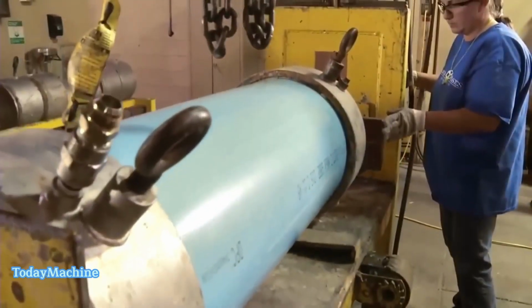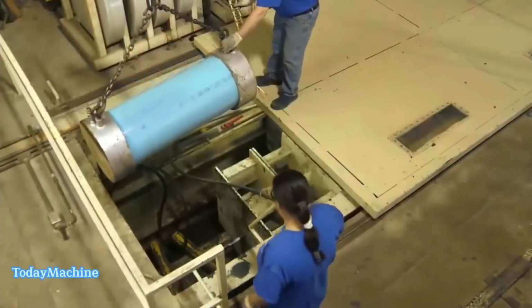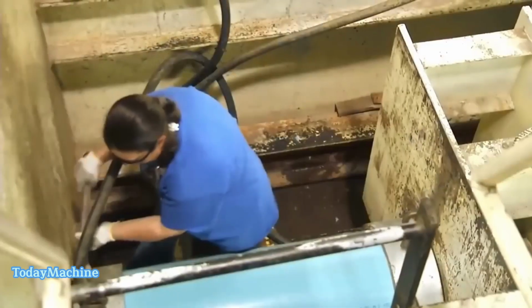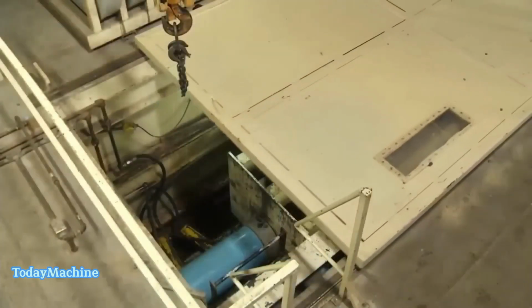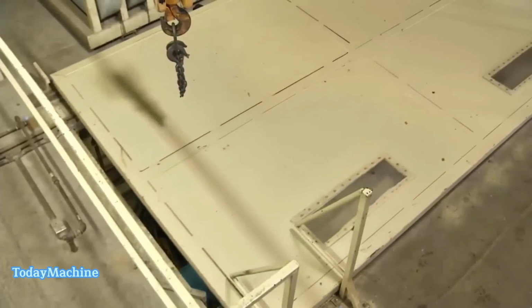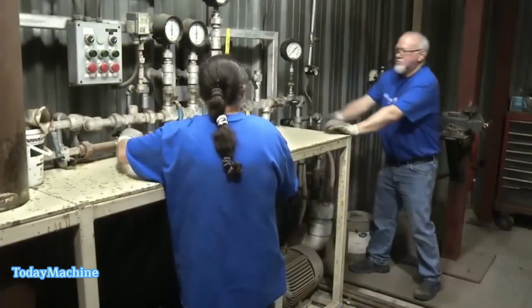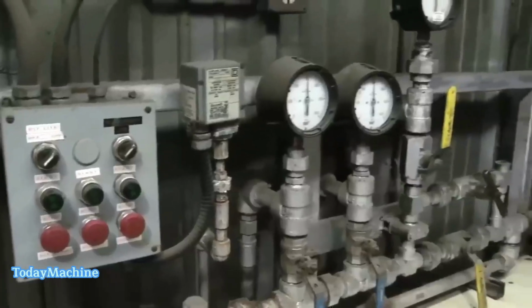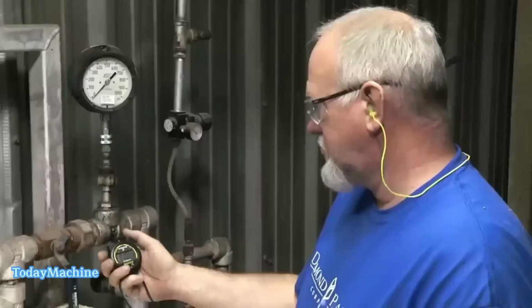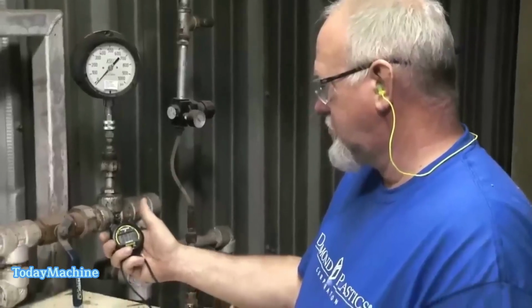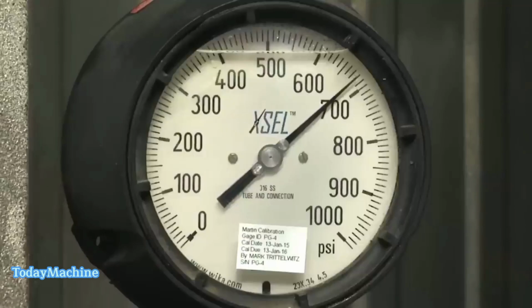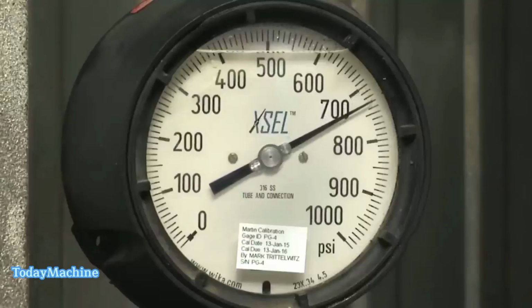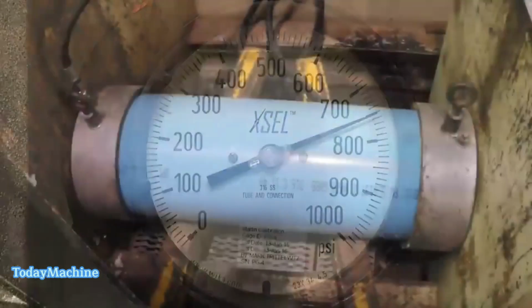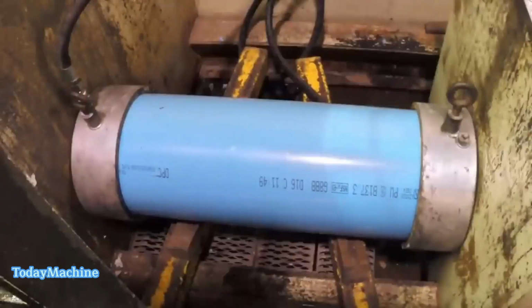To assess the pipe's resistance to deformation, flattening testing is performed. In this test, a sample of the pipe is hydraulically flattened to 40% of its original diameter, or deflected by 60%. The PVC pipe is capable of flattening until the opposite sides of the wall touch. After the pipe is removed from the flattening process, it is checked for any cracks or breaks in the material, which would indicate a failure.